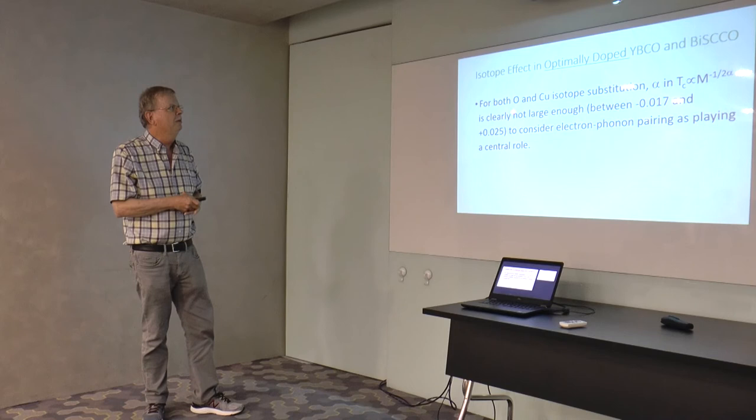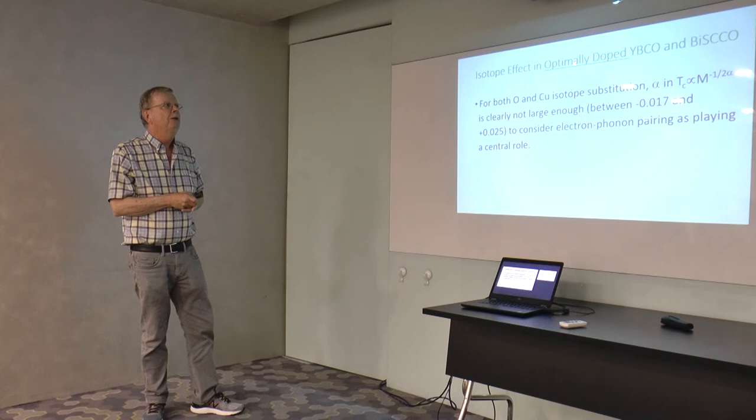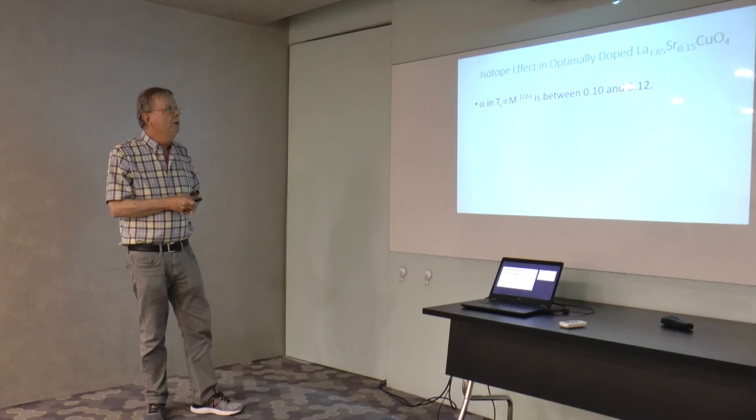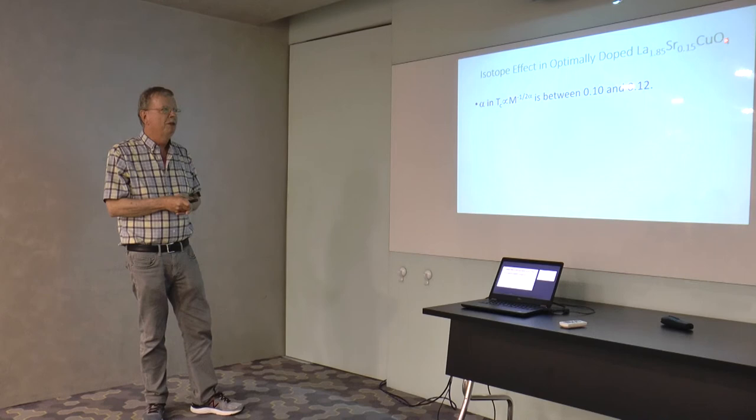So if you go to optimally doped, please, I know I'm saying a lot and sometimes I go too fast, but please remember I'm talking about optimally doped at the top of the superconducting dome. If I talk about optimally doped, there's just no isotope effect. I mean, it's just zero within their error bar, okay? However, there is a measurably finite isotope effect in 214, which I've stated before. So there is some clear evidence that there's a